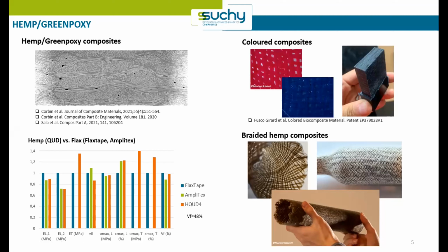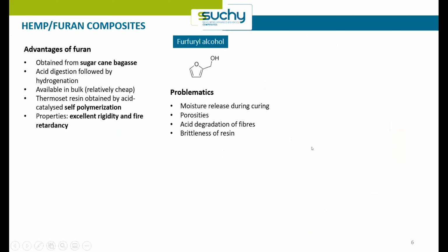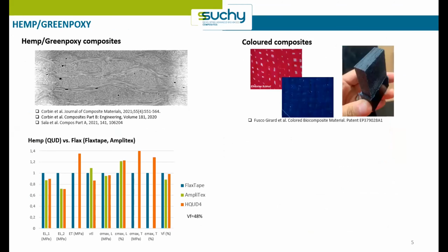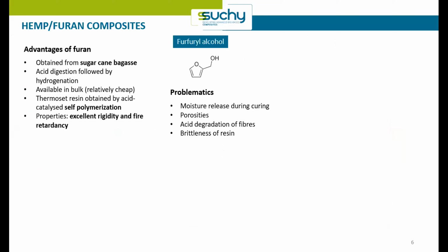On the next slide, we have the results obtained with the hemp fabrics and some furan resin. Furan was considered as an interesting polymer to obtain fully bio-based composites, since it's coming from sugarcane. It's bio-based and it has excellent rigidity and fire retardancy. We used the furan commercialized by TFC, Transfuran Chemicals. The main potential problems related to the use of this type of polymer are the moisture release during the curing, the porosities, the possible acid degradation of fibers, and the brittleness of the resin.